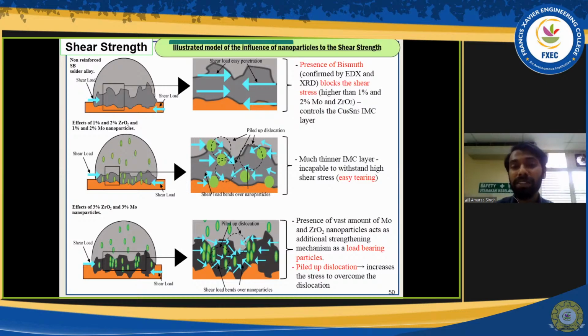Molybdenum nanoparticles are basically large nanoparticles. So they either agglomerated or they don't actually present themselves at the IMC. They might be on top of the IMC layer or very much below towards the copper substrate. That is the second diagram. So there's not much of a shearing restriction done by this type of presence of nanoparticles on top and bottom of the IMC layer. But then we have smaller size nanoparticles, especially for zirconia, and also observed for the 3% molybdenum, even though there was agglomeration of the 3% molybdenum, but they actually present at the IMC layer.